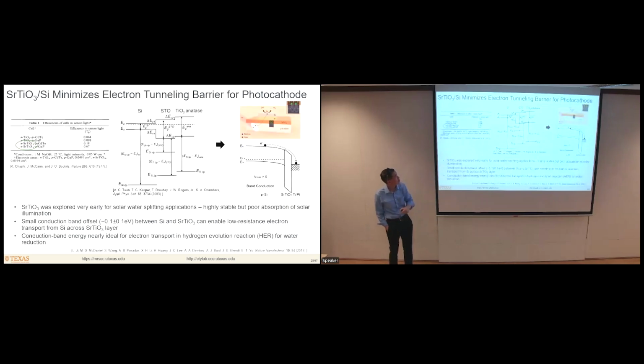And in fact, strontium titanate is a material that has been explored for water splitting applications for quite a long time, but because it has a large band gap, it's not very efficient, okay? But it does have small conduction band offset with silicon. And so what that means is that if you look at the band edge energy diagram for a structure consisting of silicon, strontium titanate, and then metal catalyst, electrons can move very easily across the structure. So that was the basic idea.